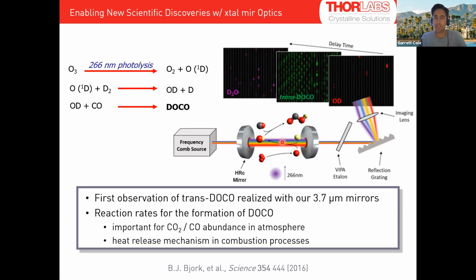So this material, trans-DOCO, but they did a very cool real-time spectroscopy experiment where they put in the reactants, initiated the reaction with a UV pulse, and then measured directly all these fleeting intermediates. Typically you write out a chemical equation and you have reactants and products, but there's a bunch of little dances going on in the middle there, and they wanted to directly measure this.